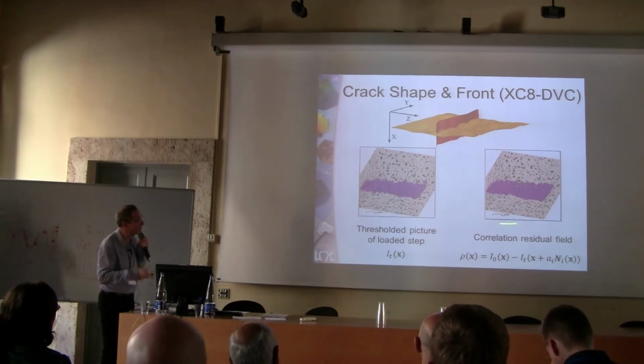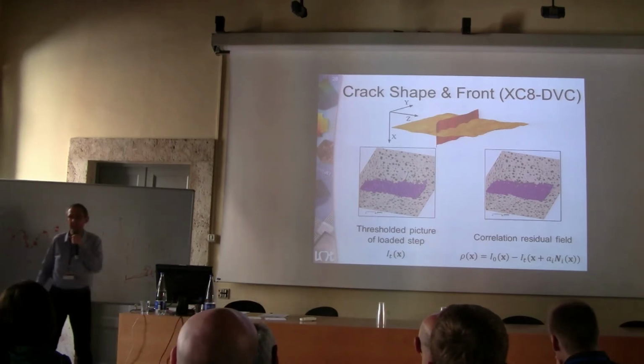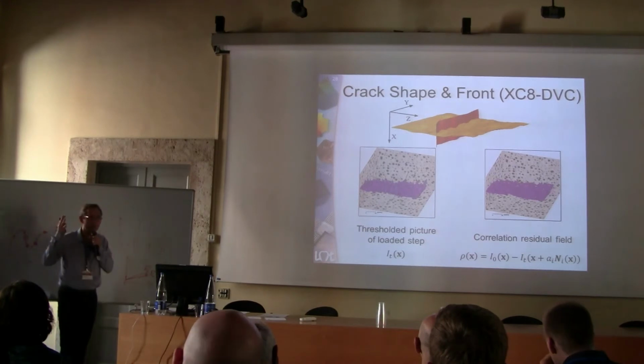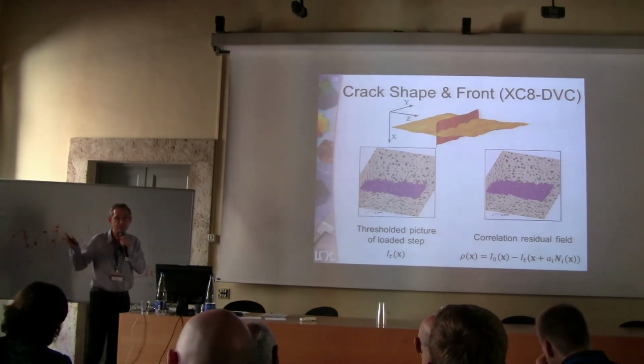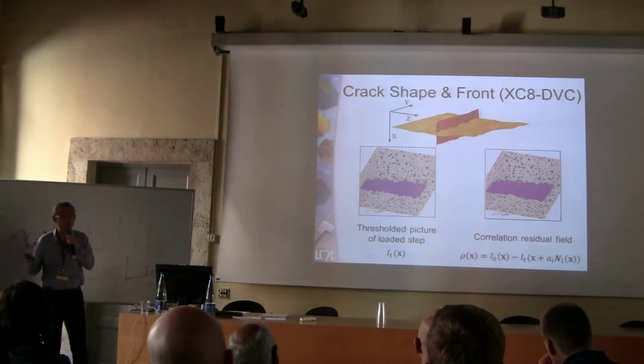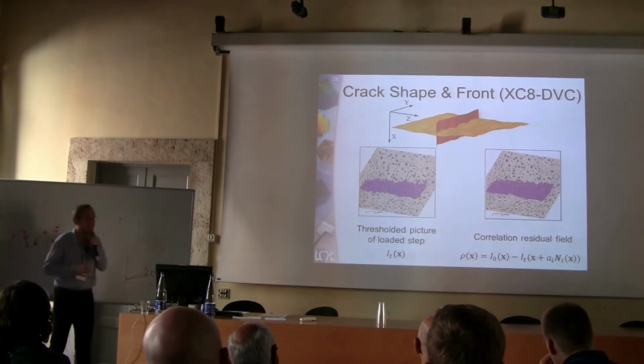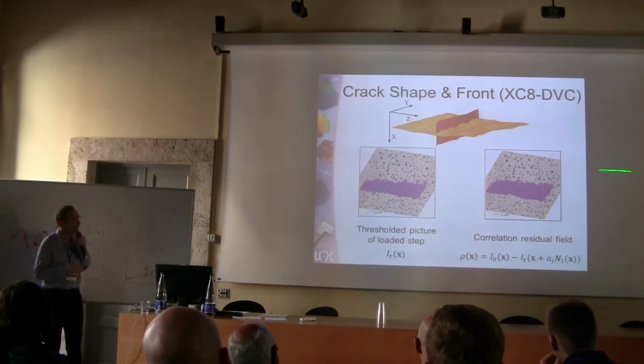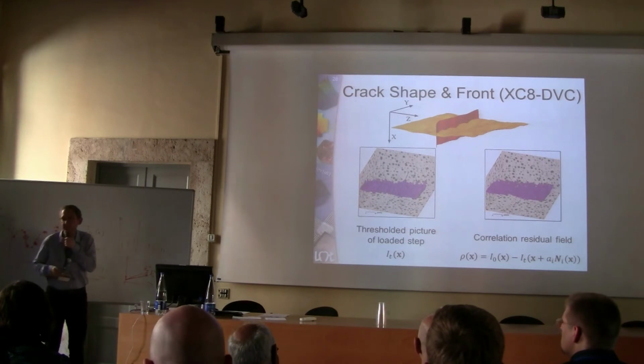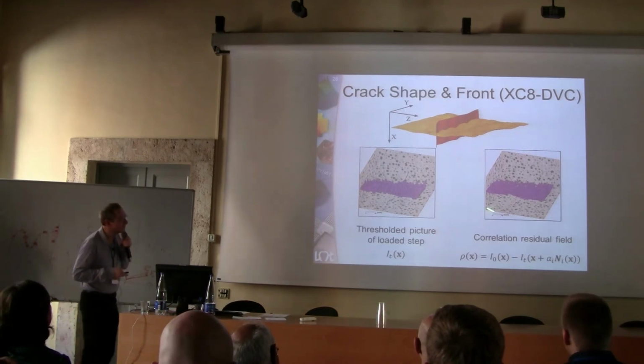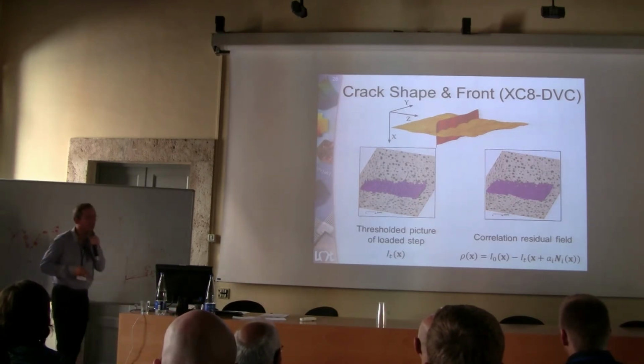Here you have a thresholded gray level residuals. We used standard FE mesh, therefore you assume continuity everywhere in the analyzed volume, which is actually true except where you have your crack.